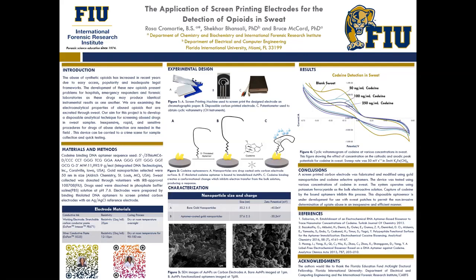Here you can see the materials that were used for this project. We used the modified aptamer, where you can see the sequence, a gold nanoparticle that was 50 nanometers in size, conductive carbon and silver paste to create the electrode, and chromatographic paper in a wax printer.